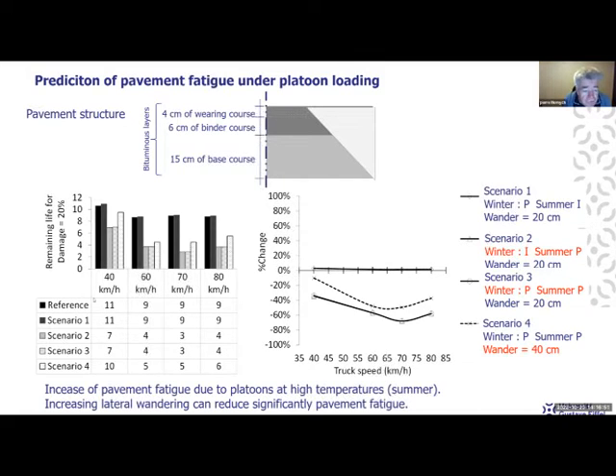And so you have the fatigue life, or the remaining fatigue life, because it was an existing pavement, for the different scenarios. And you can see that between the reference and scenario 1, when you have platoons only in the winter, there is no difference. You have the same fatigue life. In scenario 2 and scenario 3, where you have platoons in the summer, you reduce relatively considerably the fatigue life. You reduce it almost by a factor of 2. And then in scenario 4, when you increase the lateral wandering, you improve the fatigue life again, and you are not close to the reference, but you are between the reference and the worst scenarios.